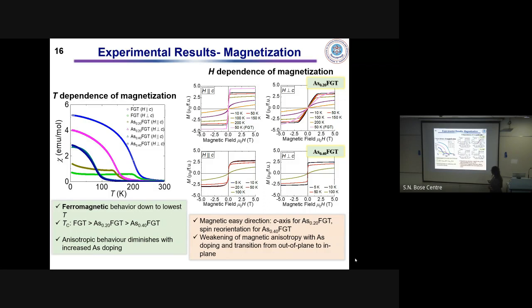From the MH curve at least, here, yes, I can understand, because there is a spin reorientation kind of stuff happening. The easy direction is moving from the out-of-plane to the in-plane direction now. But you are doing this at 5 Kelvin, and at 5 Kelvin it is very different. Magnetization and your resistance all affect that.